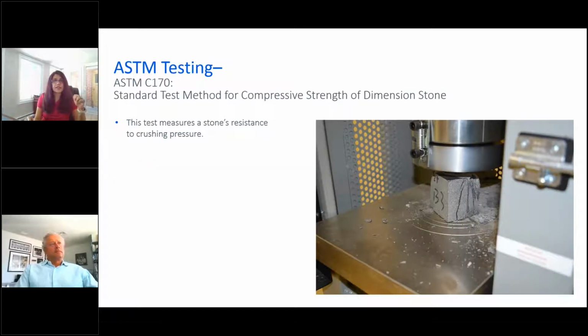ASTM C170. Now this test is the method of compressive strength of dimension stone. It measures the stone's resistance to crushing pressure. It's particularly important when we are using stone as structure. When stone is stacked for 1 story or 1.5 stories on each other, it becomes really important to know what the compressive strength of that stone is, so that appropriate height can be stacked within the safety limits.